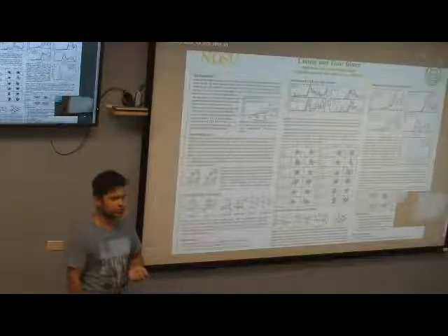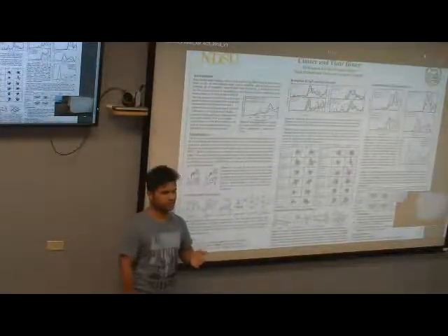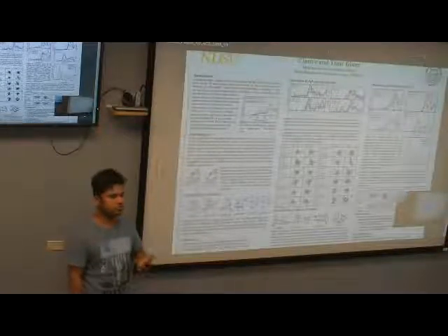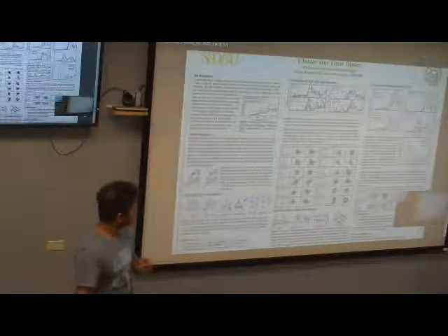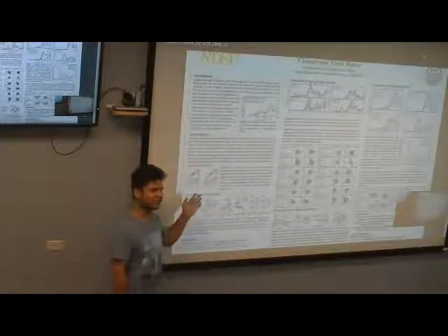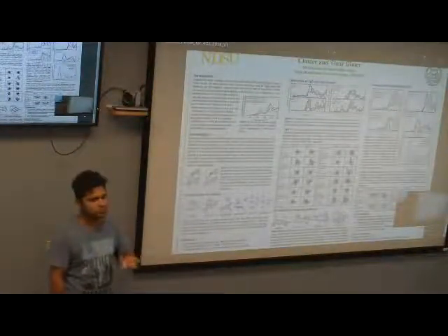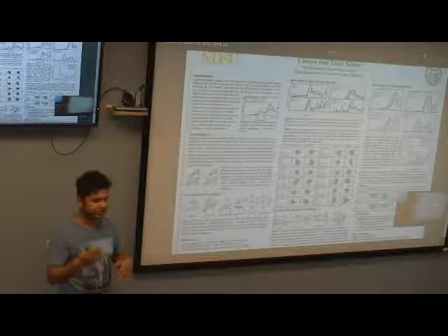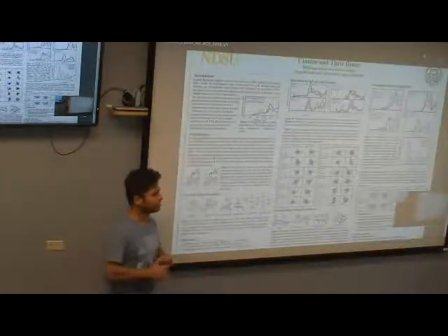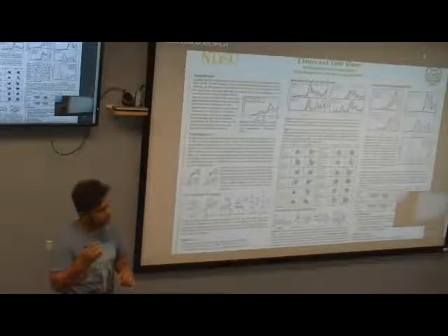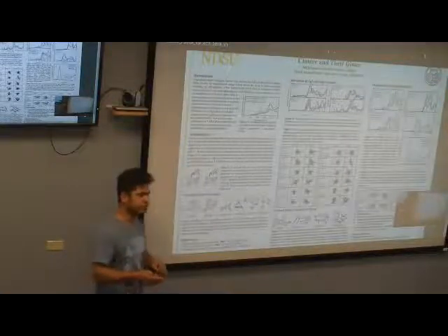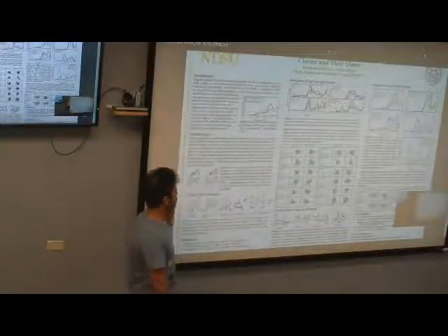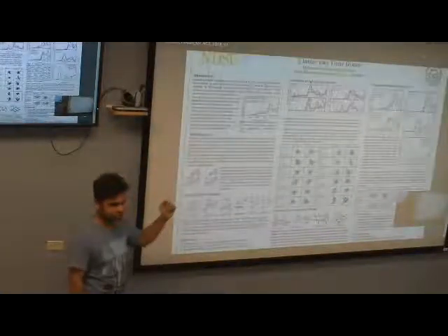The reason for using cytosine mainly is that most of the experimental results have shown that they found the emissive cluster when they use cytosine-rich nucleotides. And there are some other studies that also found that the absorption intensity or emission intensity could be increased by introducing guanine. But only guanine-rich nucleotides are not emissive, though it increases the intensity when started with cytosine. But they have no explanation of why cytosine is emissive or how guanine is increasing it. This is just an empirical result, but they don't have any concrete explanation. So we are not trying to explain that, but we use it. That's why we used guanine and cytosine in our system.